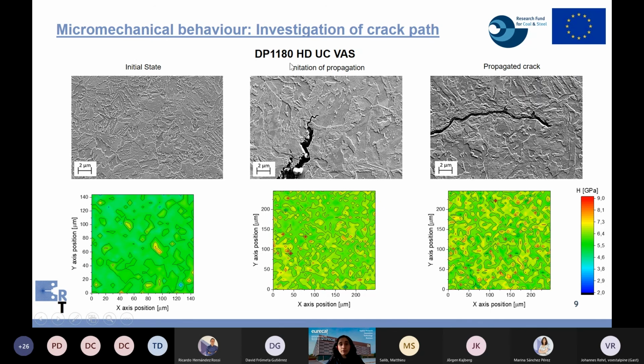In DP1180, basically, the initial microstructure consists of a bainitic matrix with blocky martensite islands, and the retained austenite is present in this microstructure, showing both needle-like and globular morphology. I want to point out the morphology of retained austenite because it is important in order to understand the fracture behavior of these third generation steel grades.